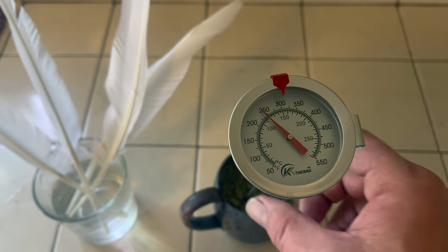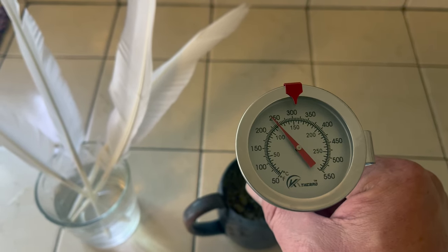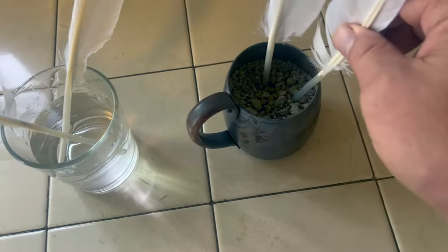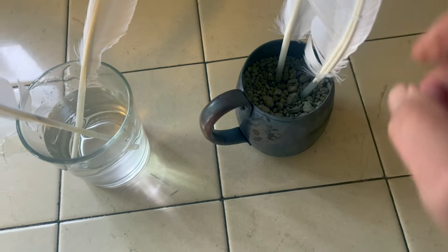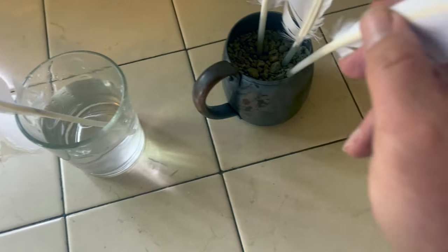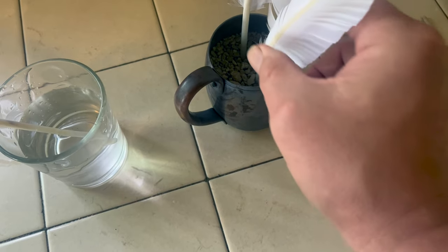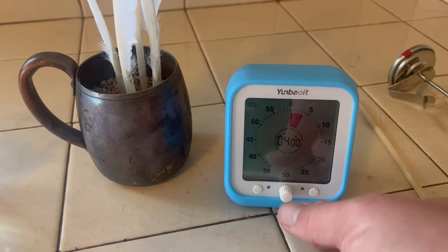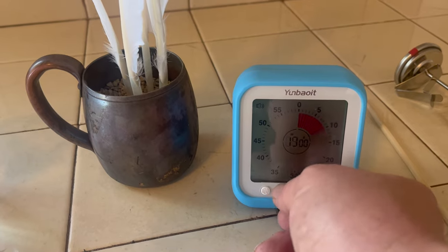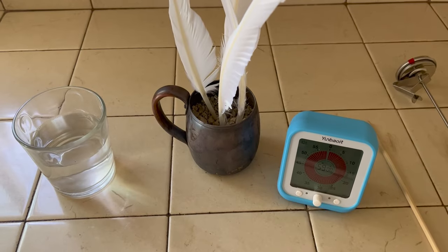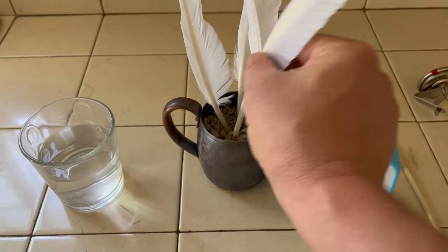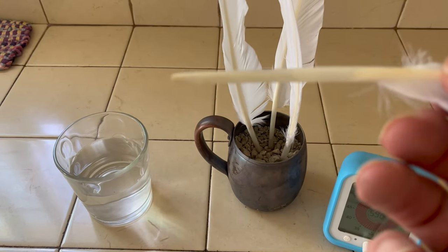Once I got the sand to 250 degrees, I stirred it to make sure that the temperature was consistent throughout and there were no hot spots. Then I stuck a few feathers into the sand, being careful not to make contact with the cup, which might burn the quill. After 4 minutes, the quill will feel much harder than before, which is exactly the effect you're looking for. If you see yellow, or worse brown, you've overcooked the feather and can toss it right into the trash.